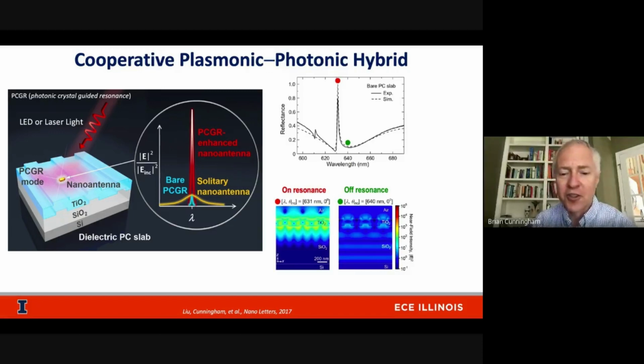The thing that a photonic crystal does that's very interesting from an electromagnetic standpoint is that when you illuminate a photonic crystal with light that matches its resonance coupling condition, the photonic crystal turns into a very high efficiency reflector, but only for a narrow band of wavelengths. If we look here at the reflection as a function of wavelength, this specific photonic crystal, made on a silicon wafer with a SiO2 glass surface and a titanium oxide high refractive index surface, is a very efficient reflector for light in the red part of the spectrum. At that resonance coupling condition, looking at a cross-section electromagnetic simulation of the photonic crystal, we see very high electric field intensity around the photonic crystal and extending into the medium like water or air on top of the surface.